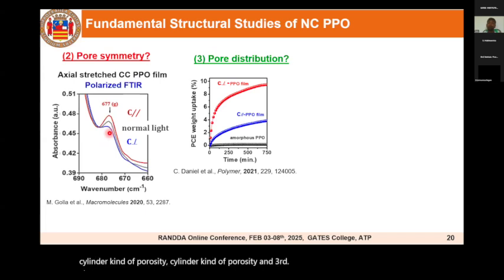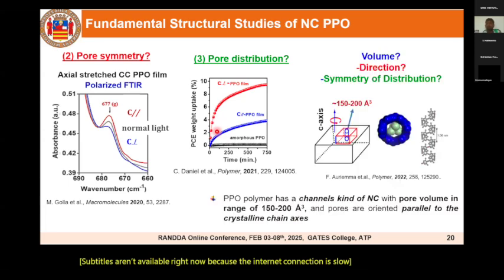And third, the pore orientation. For understanding this, we studied vapor sorption and compared C parallel and C perpendicular, which we already discussed in the previous slide. C perpendicular has very good sorption and larger uptake compared to C parallel. So this study confirmed that the cylindrical pores are parallel to the crystalline chain axis. That's the reason the C perpendicular films have very good sorption. Overall, these three studies combined give the conclusion that this PPO film has cylinder kind of cavities with pore volume in the range of 150 to 200 cubic angstroms, and the pores run along the chain axis. So these are the conclusions.